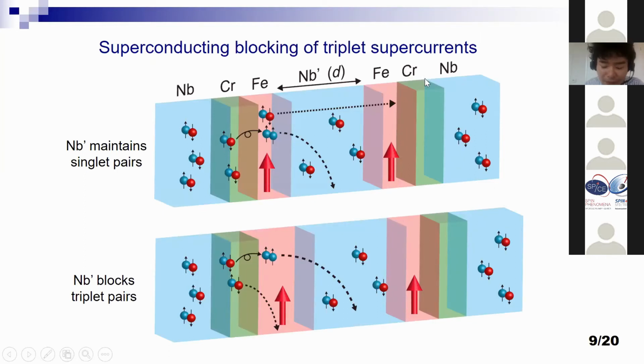So here it's a bit complicated, but we have another superconducting niobium inside the long-range Josephson junctions. Here, this niobium is in a normal conventional singlet superconducting state because we don't have a converter between this iron and the central niobium. And we can expect a totally different trend for singlet supercurrent and triplet supercurrent in this Josephson device.